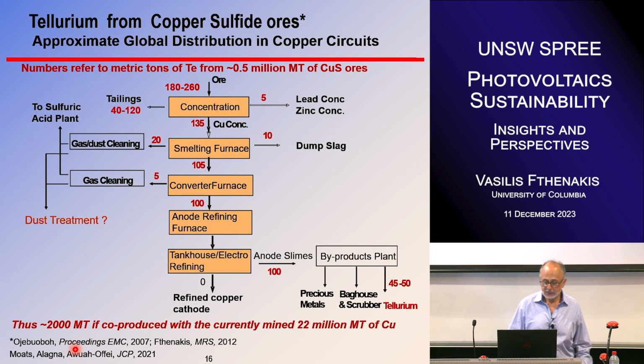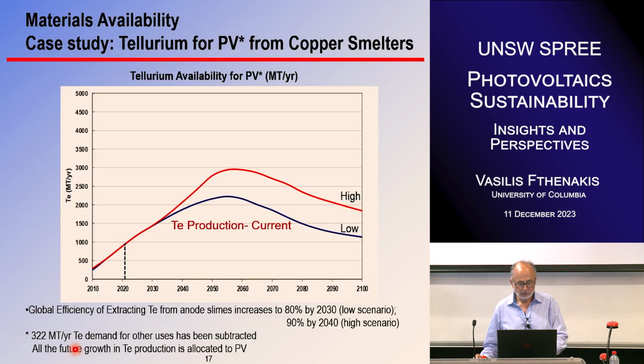But I think maybe less than half of this can do that, because copper oxide does not really include the tellurium, copper sulfide does. But anyway, I think that now we are about 600 to 800 metric tons. And again, following the scenarios of copper production that I showed before, we expect a peak at about 2060, 2070. And I have bracketed this in low and high, depending on the scenarios and also depending on assumptions about the increased recovery from anode slimes.